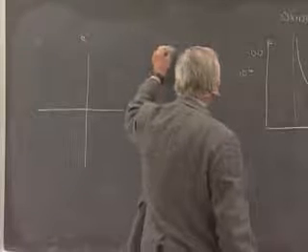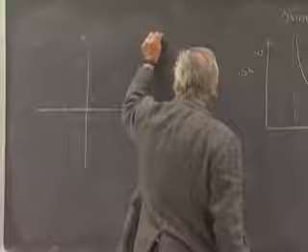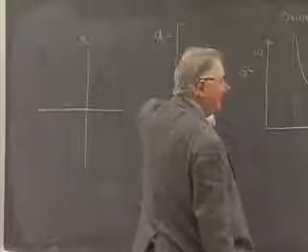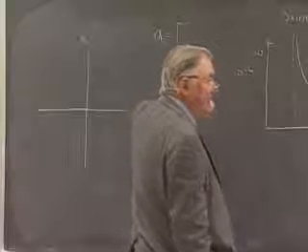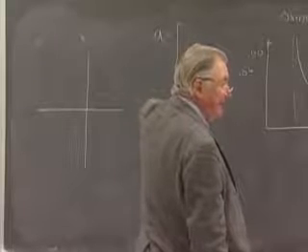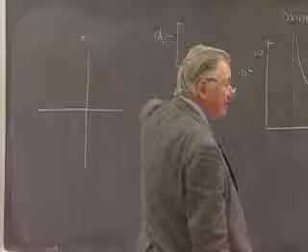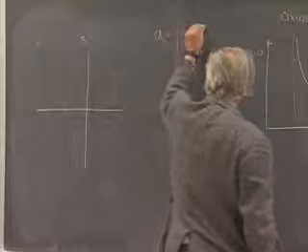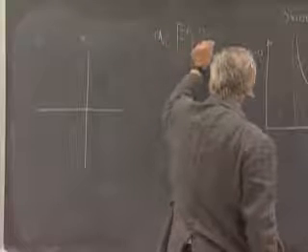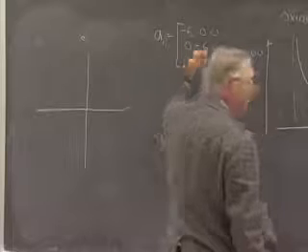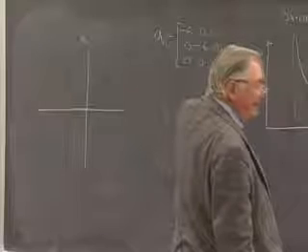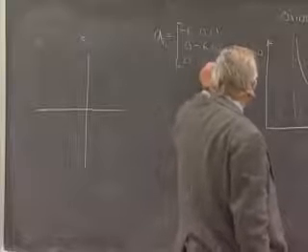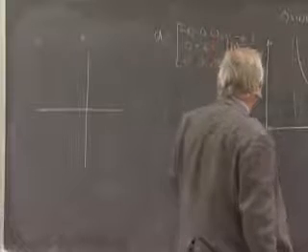parallel to C, well, the thermal expansion tensor Aij, when along its principal axes, would be along A1, and in a direction perpendicular to C, it would be, for the data given here, minus 6, 0, 0, 0, minus 6, 0, 0, 0, and A33 is 25. So that's very, very anisotropic.